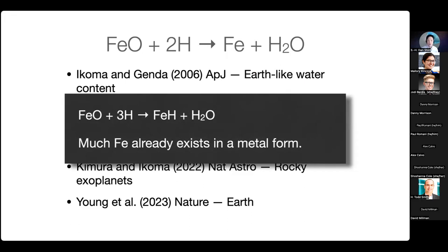The reason is that during planet formation, a lot of iron is already in metal form. So to really take advantage of this chemical reaction, you need oxidized iron, which is actually only a fraction of the iron in the system. So the oxidized iron availability would limit the amount of water that can be produced through this process. And the second thing that was overlooked by these studies is that the iron metal that forms through this reaction will alloy with hydrogen, and therefore a lot of hydrogen can be consumed through this alloy formation at the same time water is formed.